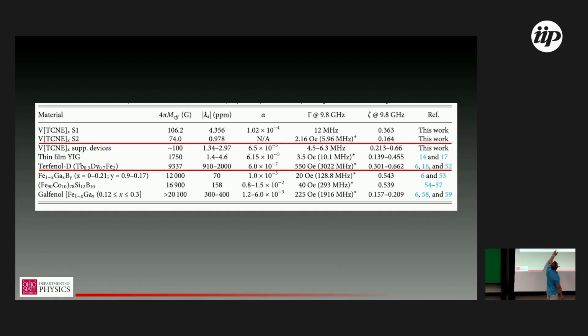And then if you look, the conventional figure of merit here is this magnetoelastic coefficient, which is about 1 for V-TCNE, about the same size for YIG, with some sample variation, structural variation. And again, 2 orders of magnitude or 3 orders of magnitude bigger for Terfenol-D. So by most conventional measures, it's not even close. So basically there is no magnetostriction in V-TCNE compared to this world champion compound.